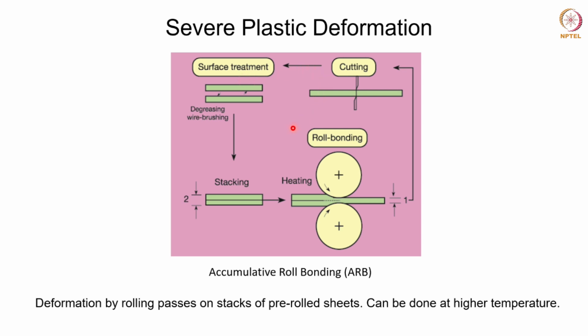So you have a stack of pre-rolled sheets, as you could see. First you cut the sheets to the required size, and then they are stacked together, and this stack of sheets is then subjected to rolling. And as the rolling is done through several passes, it will lead to bonding between these sheets and also severe plastic deformation, which would ultimately lead to grain refinement. But for this bonding to occur, this can be done at higher temperature.